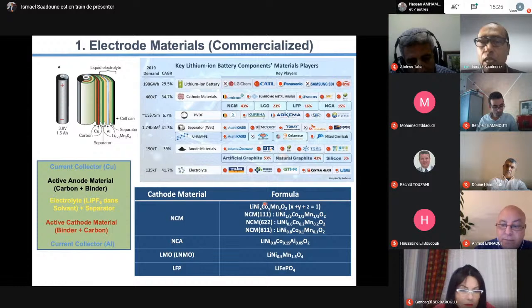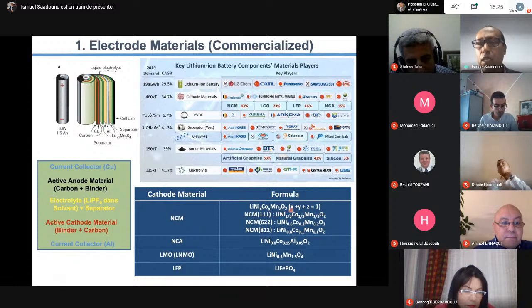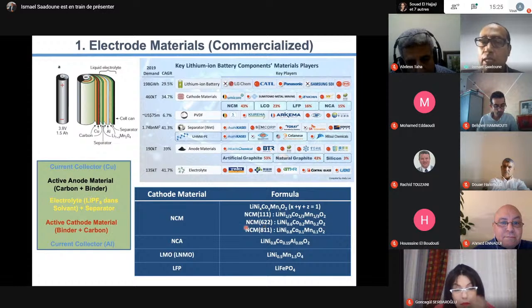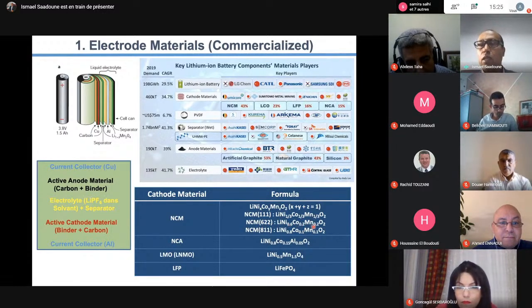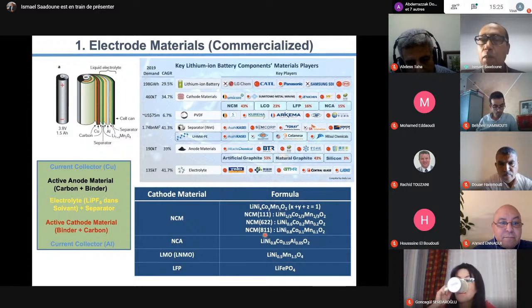NCM is lithium nickel cobalt manganese oxide with different proportions of nickel, cobalt, and manganese. Of course the quantities should sum to 1. So you can see in some cells, NCM111, this means we have equality between nickel, cobalt, and manganese. You have some NCM622, which is 0.6 nickel, 0.2 cobalt, and 0.2 manganese, and NCM811.